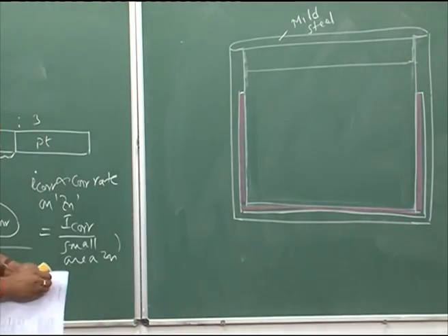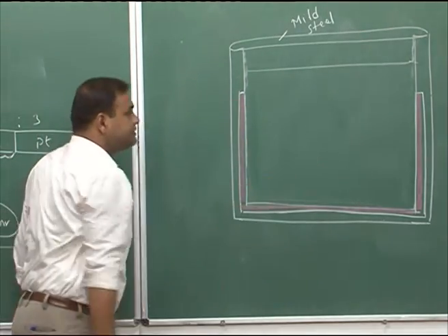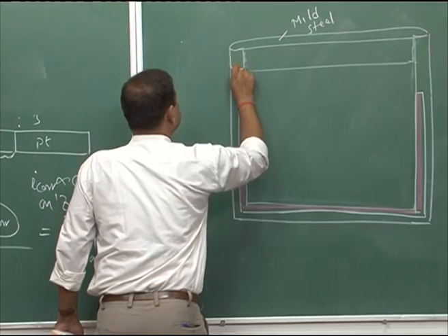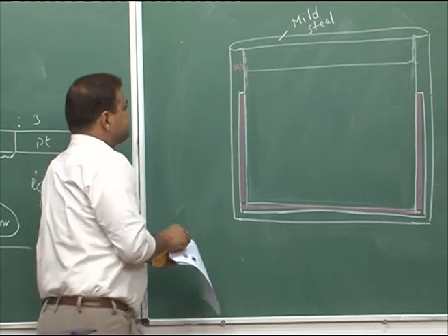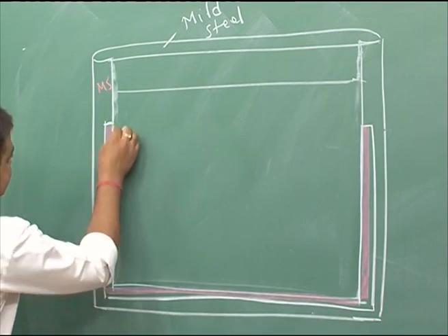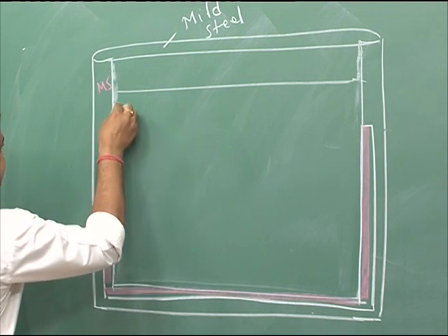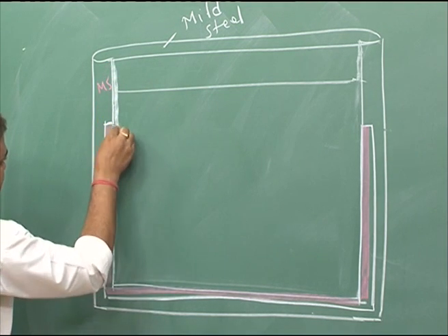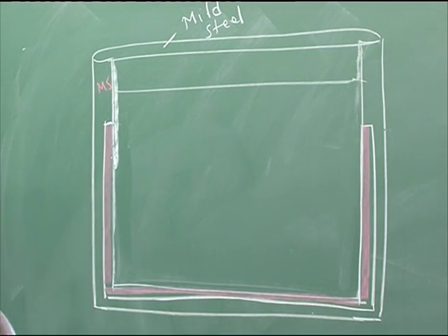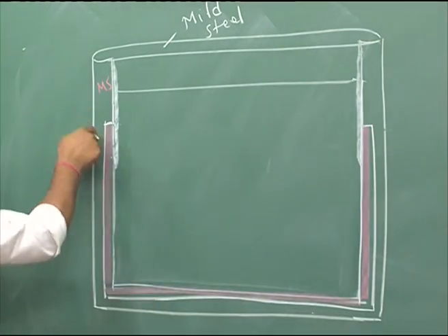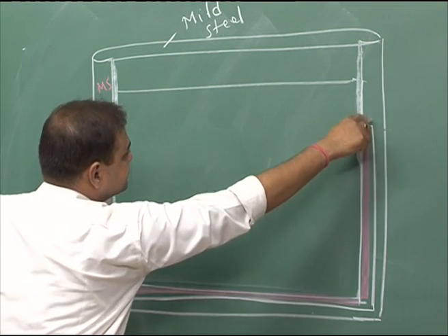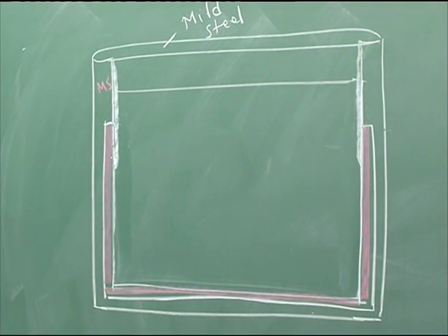This bottom part is made of stainless steel, and this is basically stainless steel clad, and the rest of it is mild steel. Since this is basically a contact between stainless steel and mild steel, we extend this phenolic coating up to a certain distance, and here also we extend this phenolic coating just to avoid the galvanic effect at this zone, since mild steel is anodic and stainless steel is cathodic as well as noble in the galvanic couple.